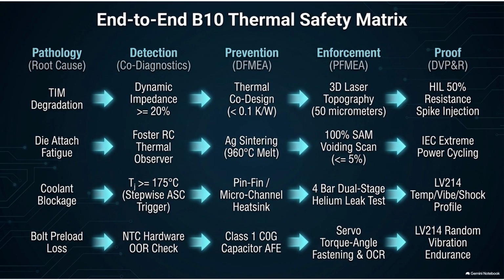And finally, the ultimate Kobayashi Maru test, hardware in the loop, or HIL, fault injection. I love this part of the document. Using an FPGA simulator or a massive physical dynamometer, they spin the electric motor to a screaming 12,000 RPM at full electrical load. Pushing it to the absolute limit. It is running at maximum capacity, pulling hundreds of amps, and then, while the system is at its absolute limit, the engineers literally pull the plug. They intentionally inject a fatal fault. They simulate an instant coolant blockage, dropping the liquid flow to zero instantly, or they simulate a massive 50% spike in TIM thermal resistance. It is the moment of truth for the entire ASIL D software and hardware architecture.